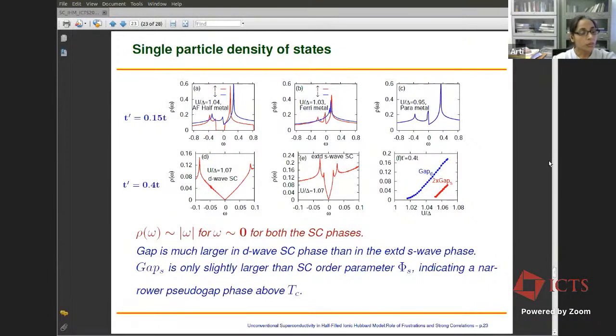Now, if you look at the peak-to-peak spacing in the density of states for the superconducting phase, which gives you basically a superconducting gap, this gap increases monotonically as a function of electron-electron interaction, both for the D-wave superconductivity as well as for the extended S-wave superconductivity. But this gap, as you can see, is much larger than the superconducting order parameters, which again indicates that the system must be having a large pseudo gap phase.